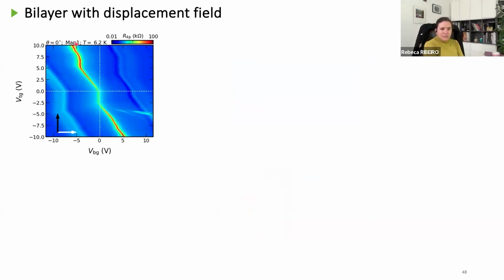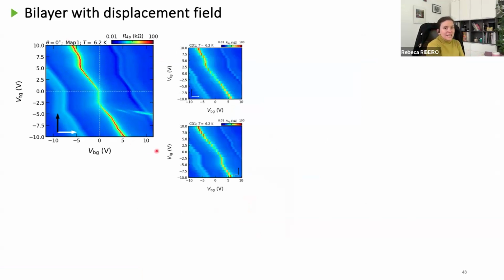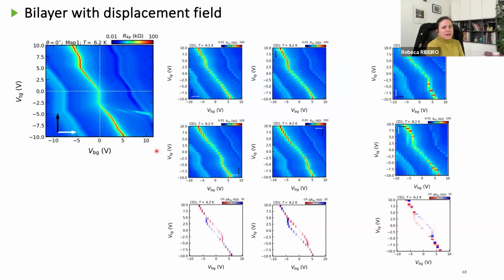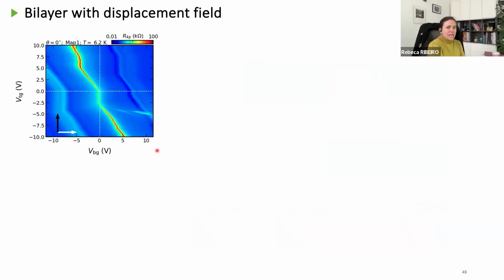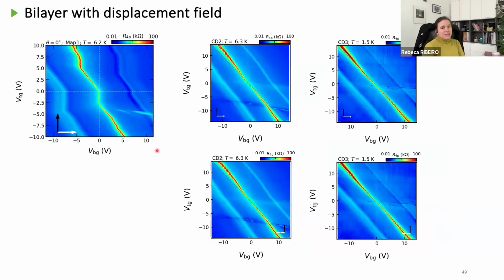We can observe this erratic behavior of the gate, which is associated with the ferroelectricity. In this case, both gates are symmetrical, which is different than before. But more importantly, when we are aligned and we observe this ferroelectric state, it's a very unstable state.